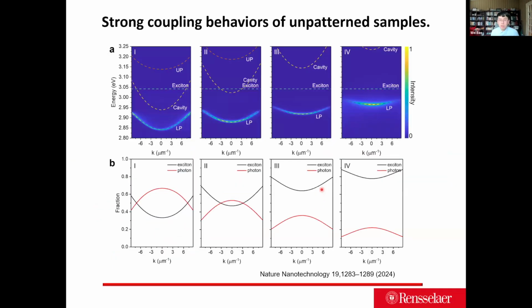And from the unpatterned sample, we can see, even though the upper polariton is unseen because of the larger polariton Rabi splitting, the flattening of this polariton mode once it's really close to the exciton line, and then one can also extract the Hopfield coefficient of this polariton mode.